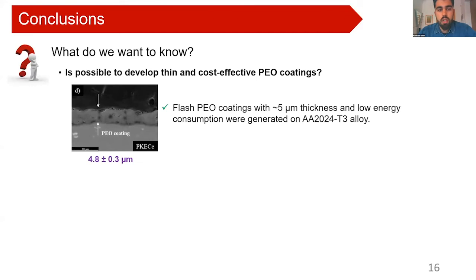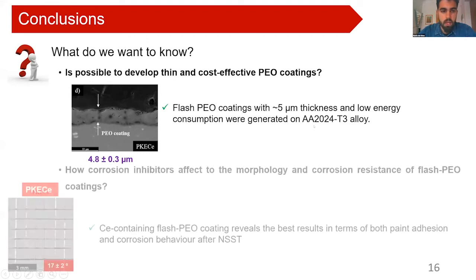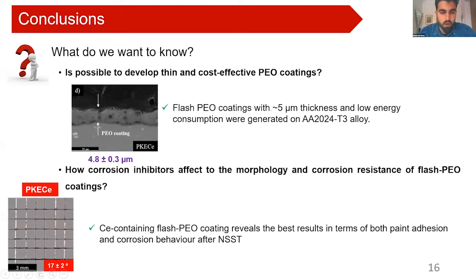So in conclusion, it's possible to develop thin and cost-effective PEO coatings with thickness comprised between 4 and 6 microns and low energy consumption on 2024-T3 aluminum alloy. Also, regarding the incorporation of corrosion inhibitors, we ascertained that the cerium-containing flash PEO coating reveals the best results in terms of both paint adhesion and corrosion behavior after the neutral salt spray test.